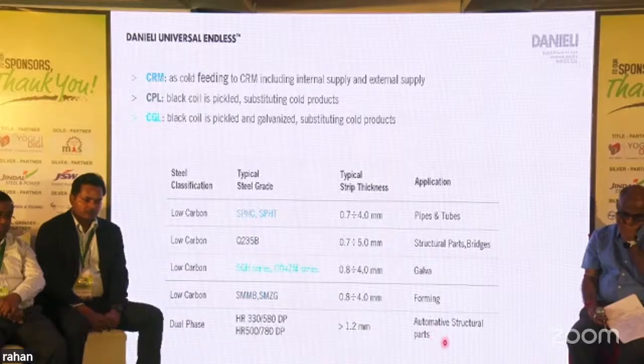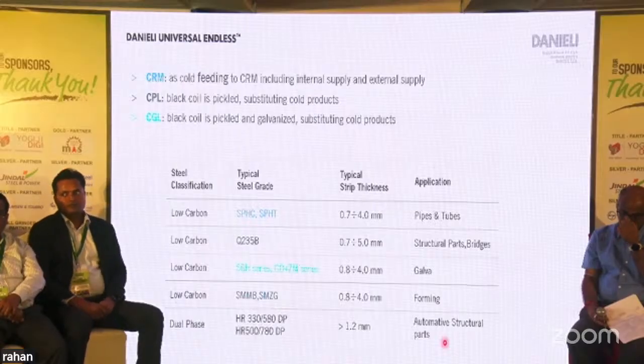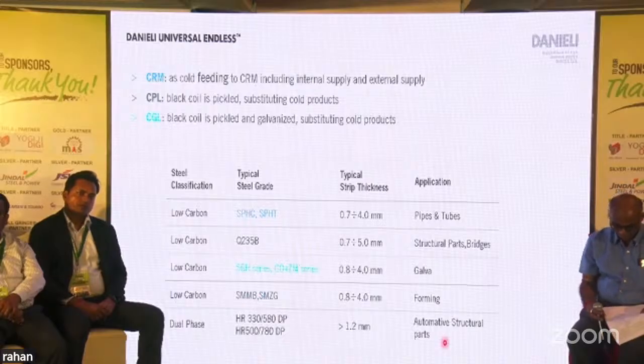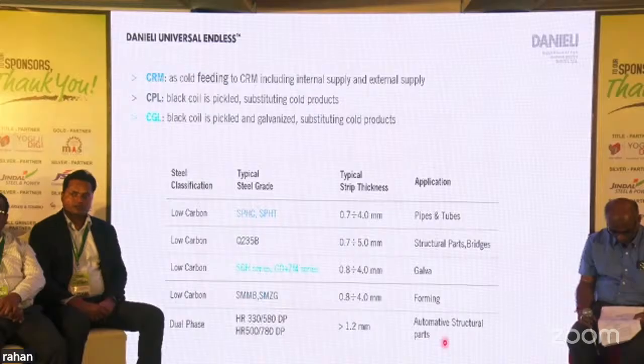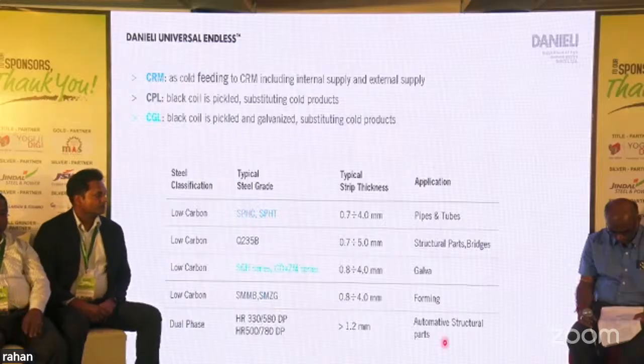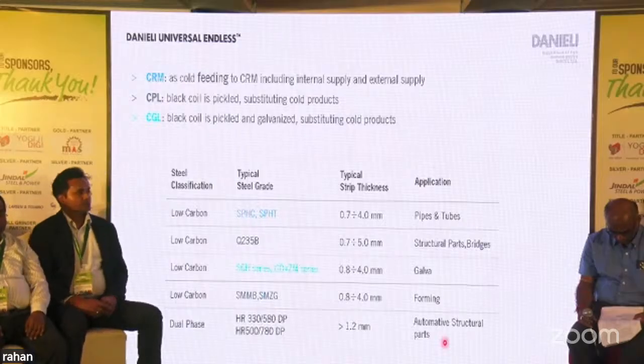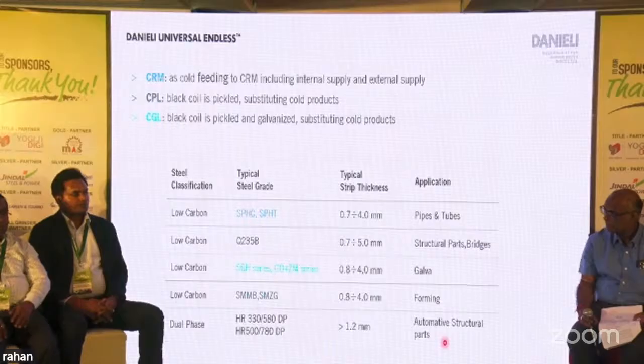So what I would like to highlight here is that the hot rolled coils were naturally going to cold roll mills for a further reduction, and then they were being coated or processed to meet certain requirements. But if the requirement of thinner gauge is fulfilled by the hot rolled coils, it can avoid certain amount of reductions in the cold rolling mill, and thereby you save some energy. And at the end, when you talk of carbon emissions per ton of finished steel, you are reducing it.